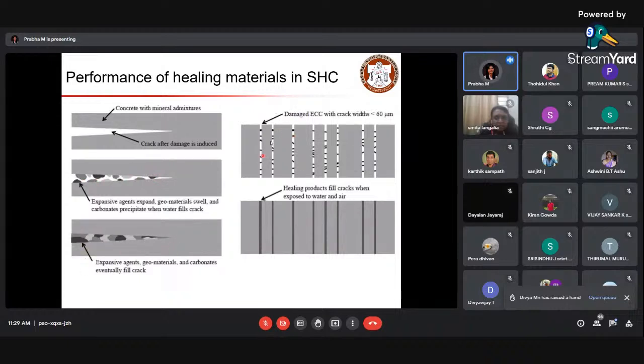When you look at the images in the longitudinal view, you can see damaged ECC with crack widths less than 60 micrometers, all healed by the healing products which filled the gaps or cracks when exposed to water or air.